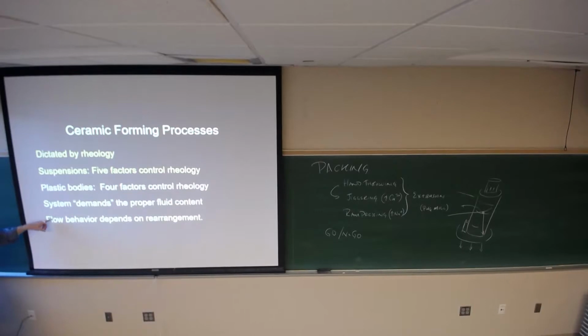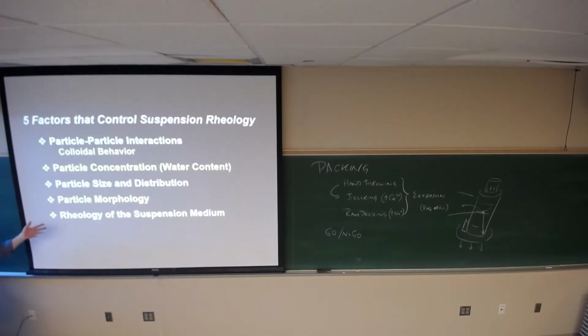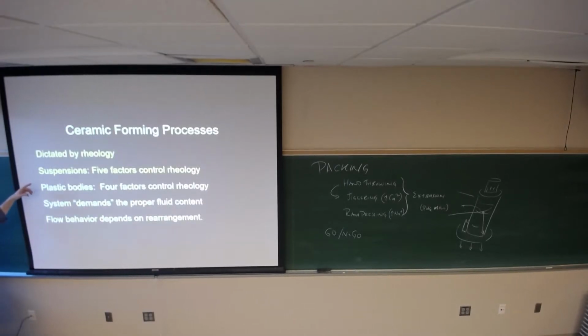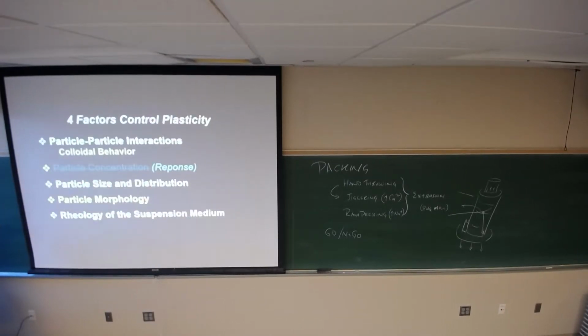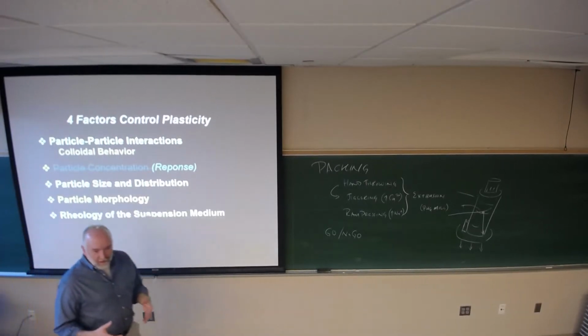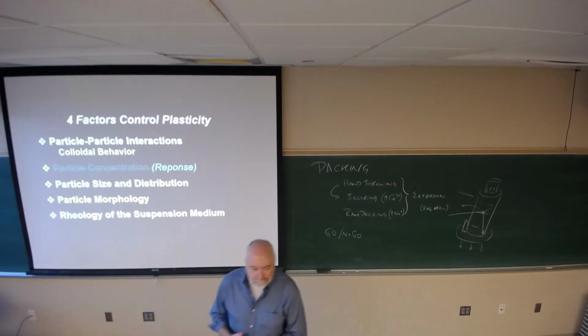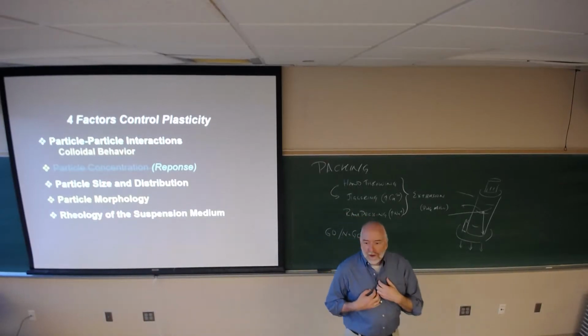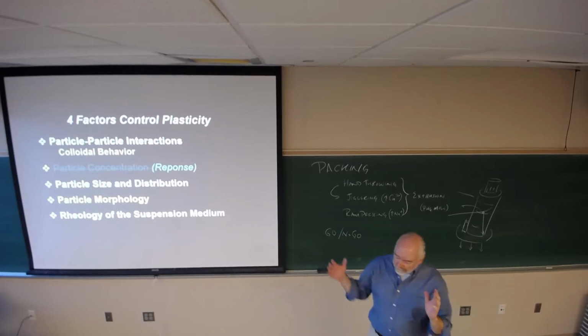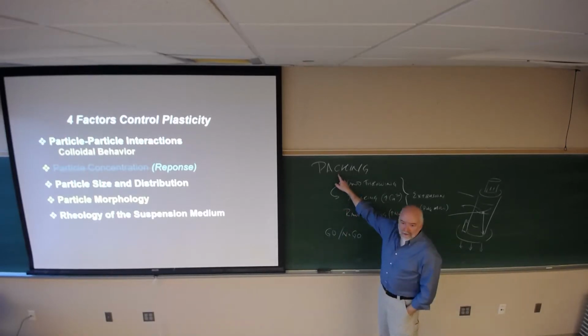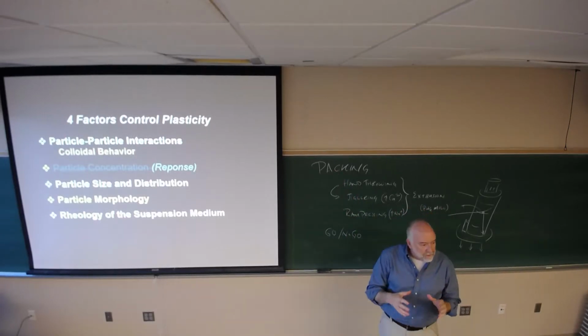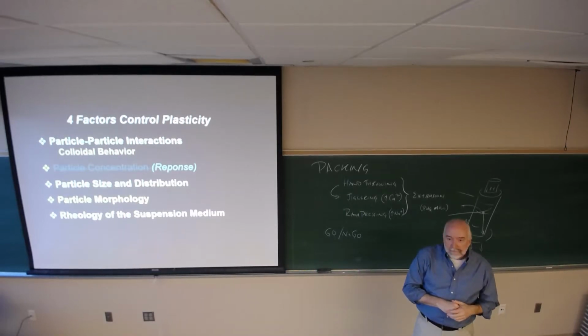And then the flow behavior depends on the ability of the room for particles to rearrange. So I have the 5 factors that you know. When I go to forming processes, I go to here, 4 factors. Particle concentration now, which is the water content in the system, is a response, not a variable. We want to act like we control the water content. We do not. So what you get is this packing behavior dictates how much water is necessary to fill the pore structure. Okay? If I improve the packing, I require less water to fill the pore structure.